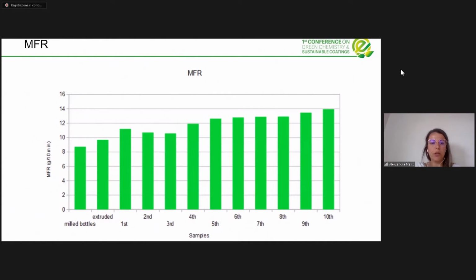As you can see, except for this first cycle of injection molding, which we cannot explain, all of them are rising. As expected, due to reprocessing and consecutive processing of the material, there is some degradation occurring, and the chain length is decreasing. So the melt flow rate is increasing, but the increase is not so high. If you consider all the cycles, so there are actually 11 thermal processing cycles, the melt flow rate rises 50 or 60%.